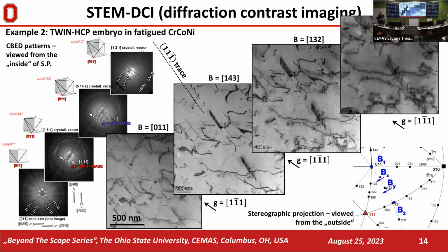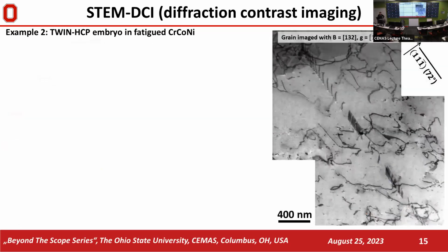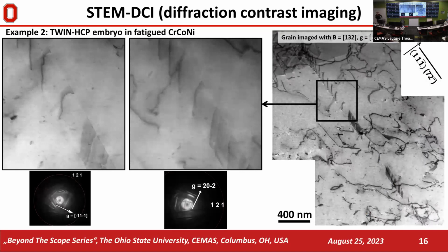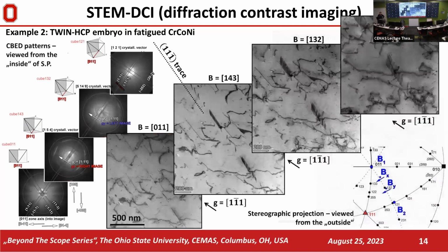This gives us the same opportunities as in the past with conventional TEM, and we can see the defects very nicely resolved. And if we focus on individual dislocations, when we take a look at this map, this is what I was talking about when using site and orientation specific foil preparation, this is what you can reach. If you prepare the sample properly oriented already using your dual beam system, then you know what to expect, what kind of opportunities you'll have to collect the information about defects in your studied crystal.